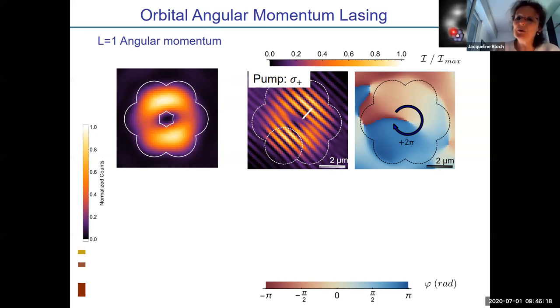Of course, we cannot do interferometry between this lasing emission and the excitation laser because they are not at all at the same energy. So this is why we are going to use part of the emission as a phase reference. And we will measure the phase difference between each lobe and the one that we have chosen as a reference. So this is the phase pattern we observe directly. These are raw data that we see directly on the CCD camera when pumping sigma plus. And we can, by Fourier transforming this image, recover the phase and access the phase of the different lobes.